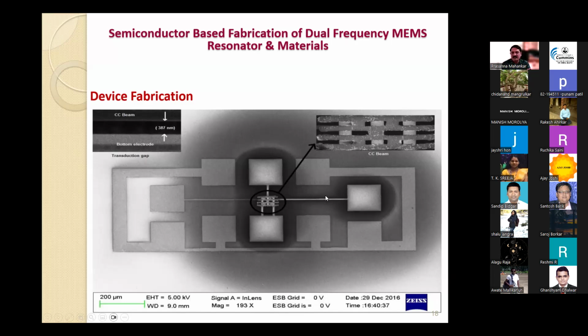Here we have done measurements, and the gap between the CC beam and the bottom electrode was measured to be 387 nanometer, which is approximately 0.4. So this particular structure we have fabricated, and this is an SEM image that was obtained at IIT Bombay. This fabrication, we got it after 3 iterations and it took almost 6 to 7 months to finally get this. We had different problems regarding fabrication, which we will talk about someday later on.